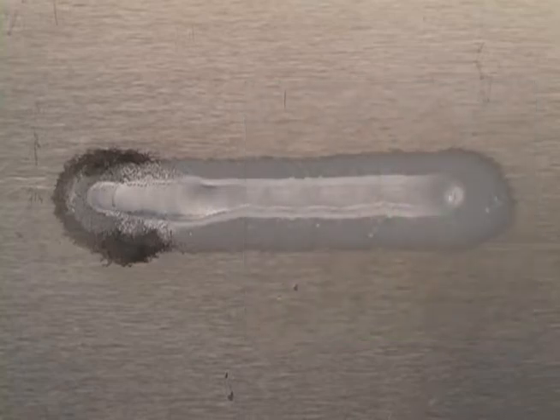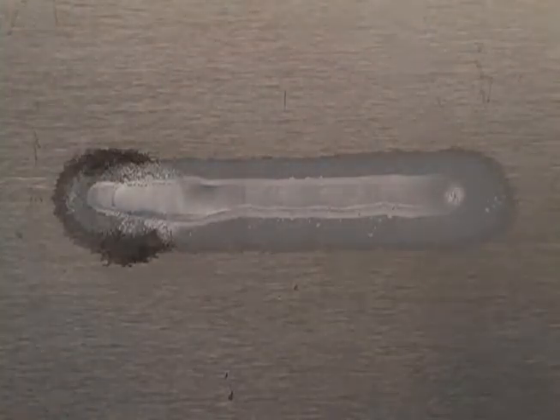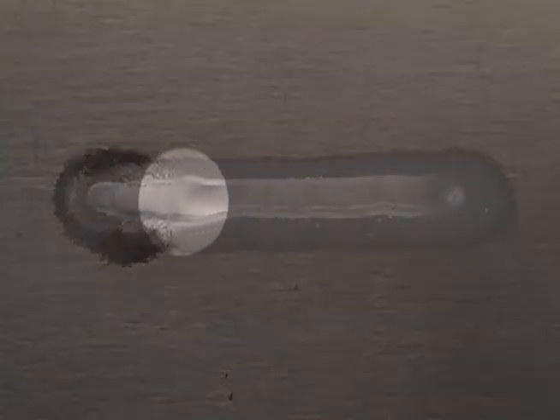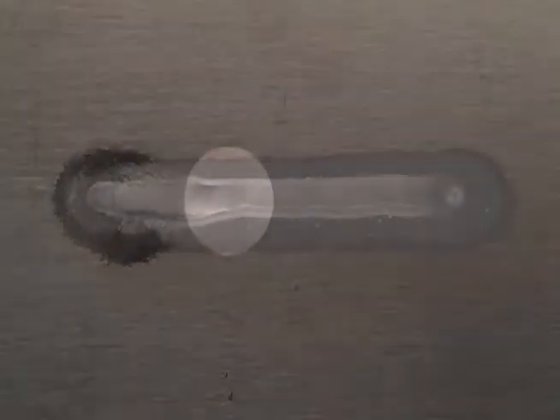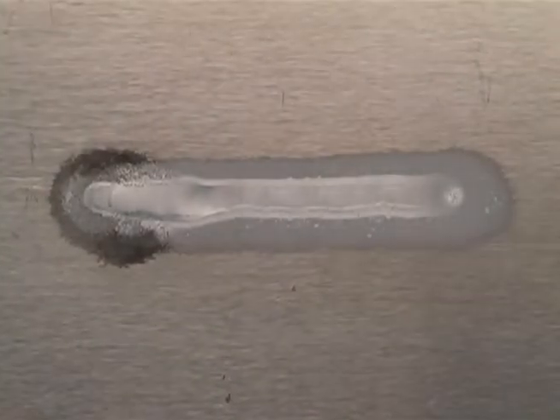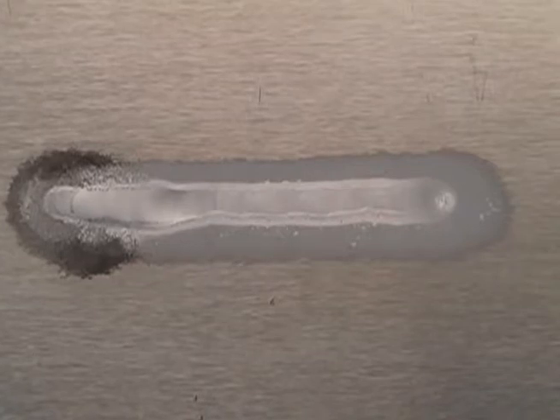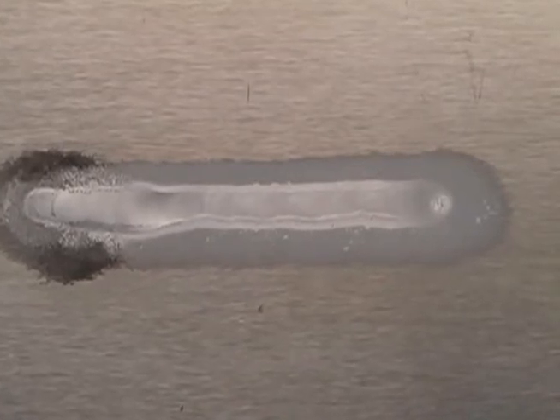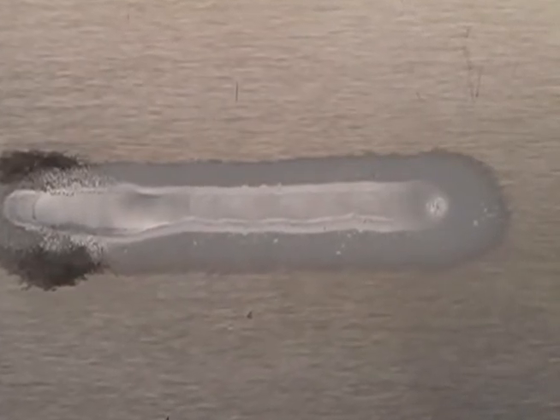bead continues. You can also see I failed to back the pedal off to compensate as the aluminum heated up and the bead is too wide, and then it starts to fall away from excessive heat. The last segment of the weld is very nice, very consistent bead width. I have picked up the travel speed and backed off on the pedal to achieve this.